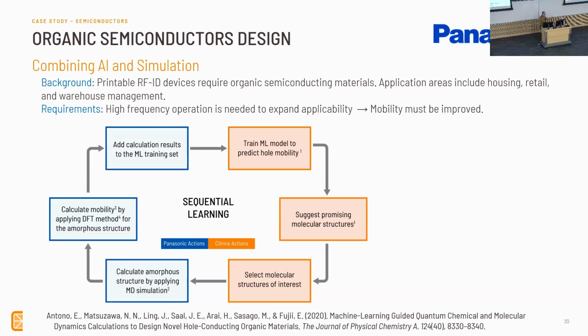That'd be too much. So what we did is the right half of this workflow was to basically train a machine learning model to be a surrogate for the expensive DFT. And so our experiment, quote unquote, is the DFT. How well can we make a model to basically reproduce the DFT and then identify within the hundreds of millions of molecules that are candidates, what are the best ones to do DFT on. And then we just iterate on this until we come up with something that's good.